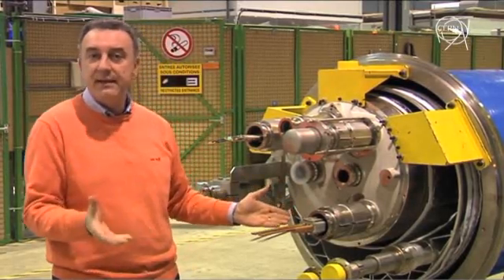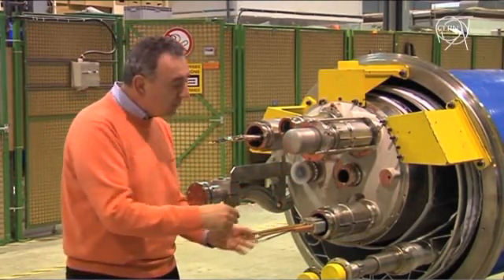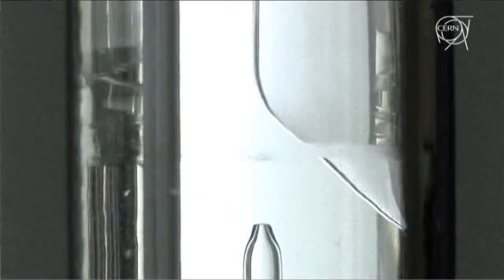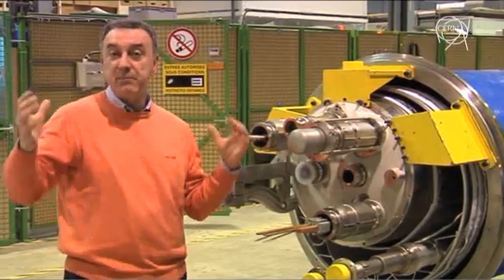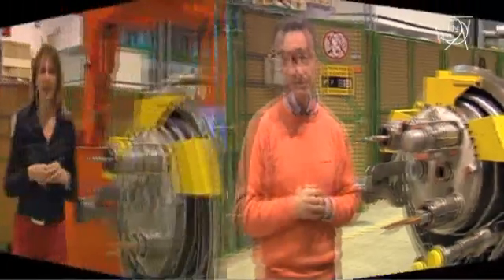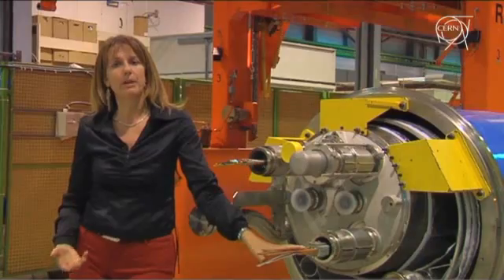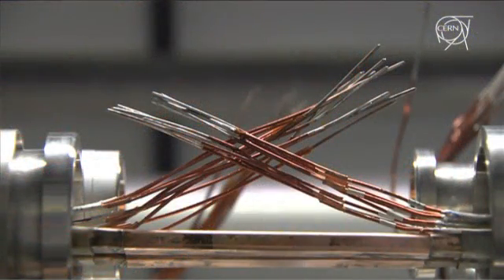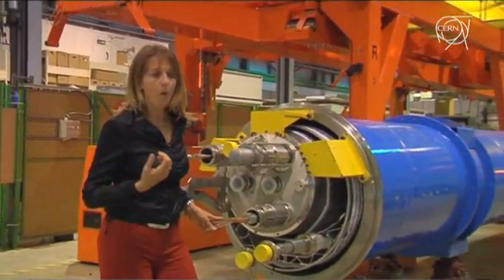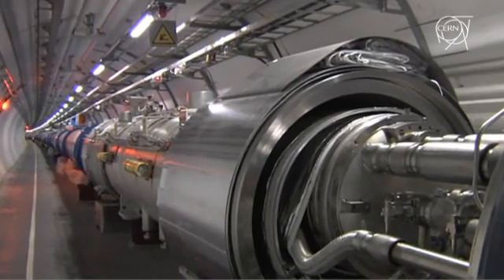In an electrical machine like the LHC, with the energy stored in the magnets, when you develop an arc, we are done. We lost two nearby magnets, and because of the pressure wave of helium — there is superfluid helium inside this closed enclosure — the electric arc perforated the enclosure, allowing helium to enter the vacuum chamber. The helium, which is very cold, immediately gets hot and expands, generating a pressure wave that did a lot of damage to many magnets. It was this electrical interconnection between two superconducting magnets that melted during electrical tests on September 19th. There are 20,000 such interconnections in the LHC, all with record-breaking performance requirements. This created the leak of superfluid helium which damaged 53 dipoles out of the 1,232 that make up the 27 kilometres of the LHC machine.